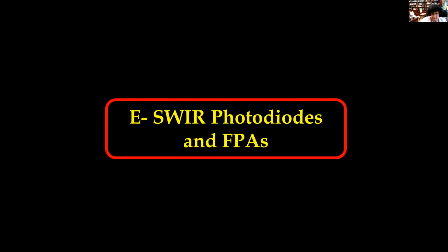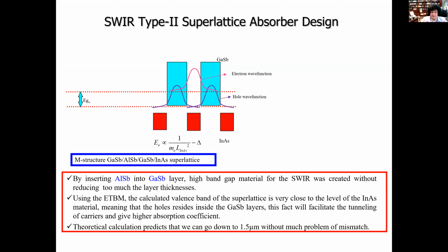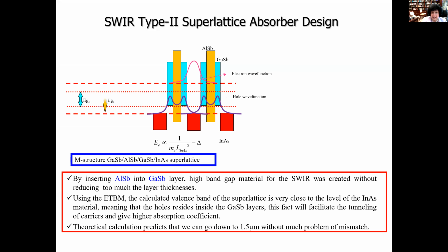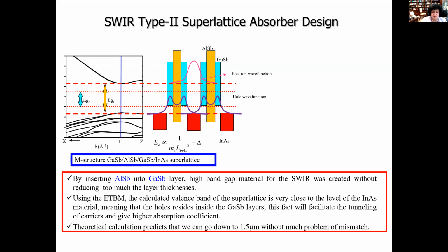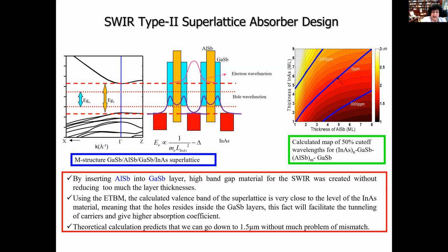Now going to the short wavelength. Again, how can we come with this material of gallium antimonide, indium arsenide, to go to the short wavelength? I mentioned how we can go to the long wavelength, but for the short wavelength, again by doing atomic and gap engineering, putting a few monolayers of aluminum antimonide inside the gallium antimonide, we can say that, okay, that is the M structure, and we can see that by that we can increase the gap and go to the short wavelength material.